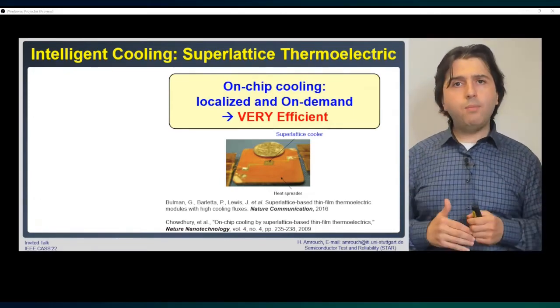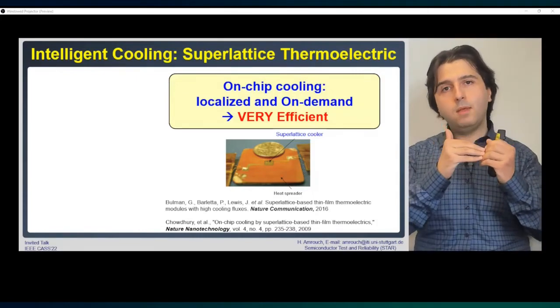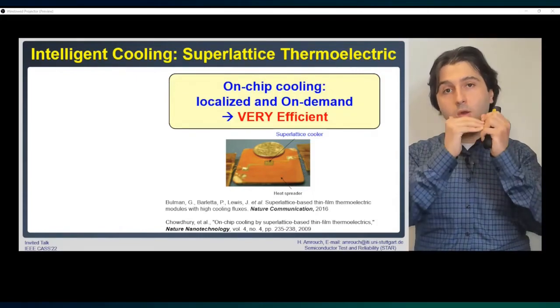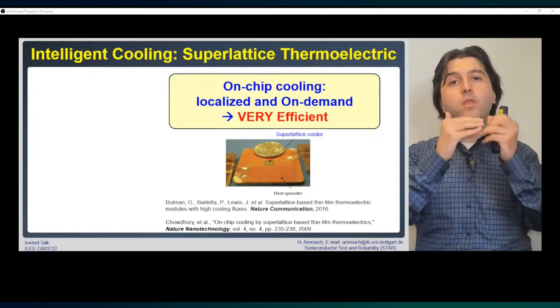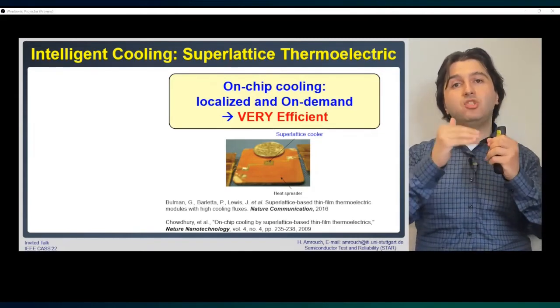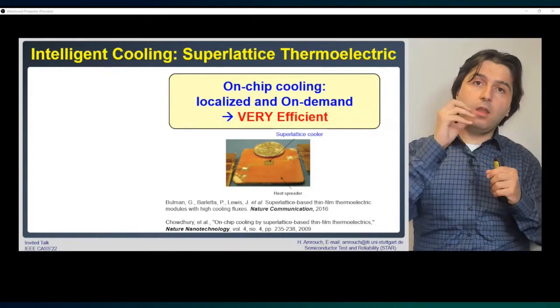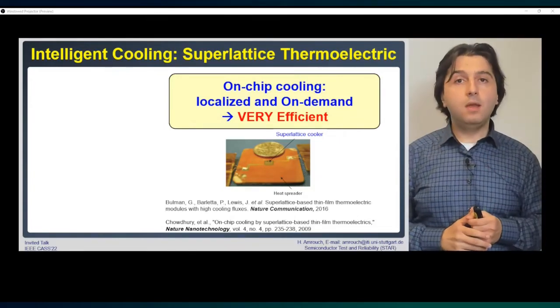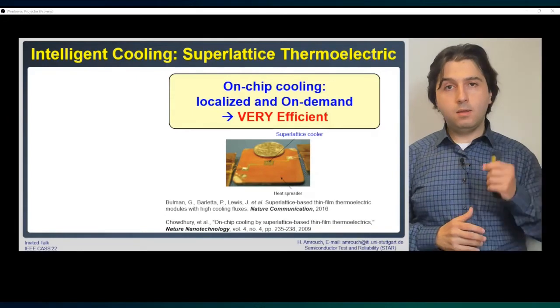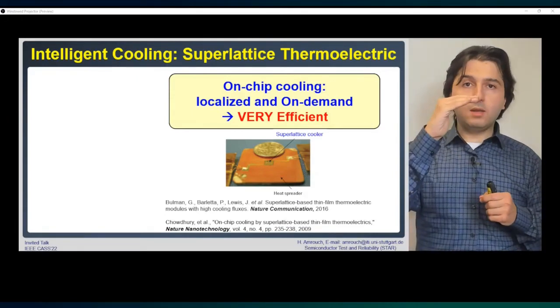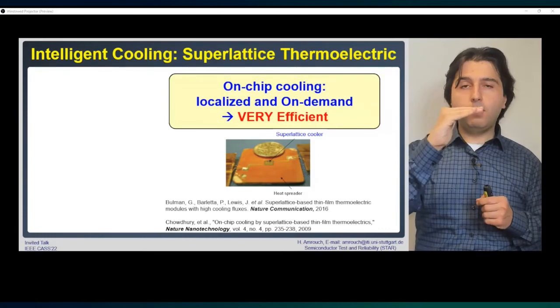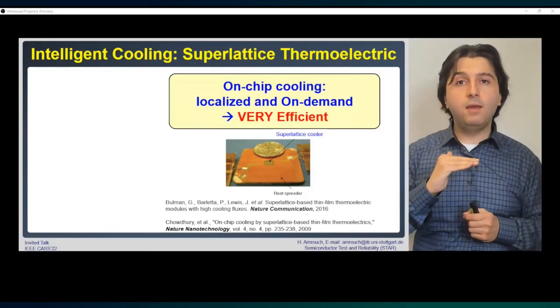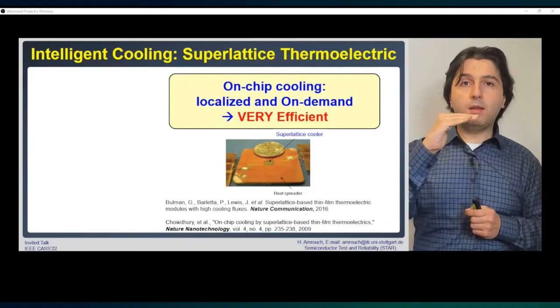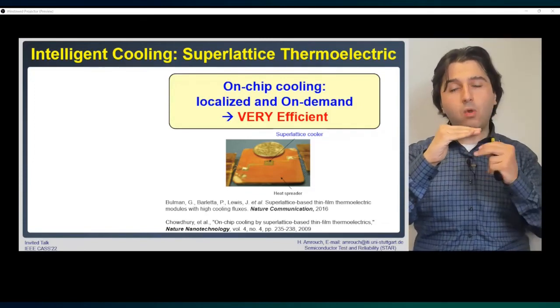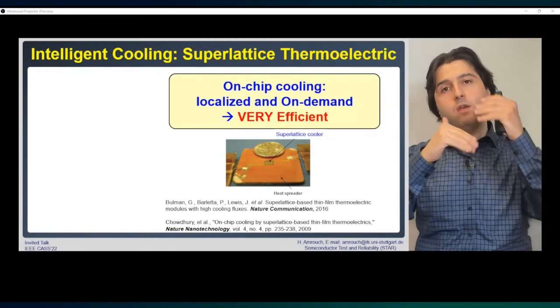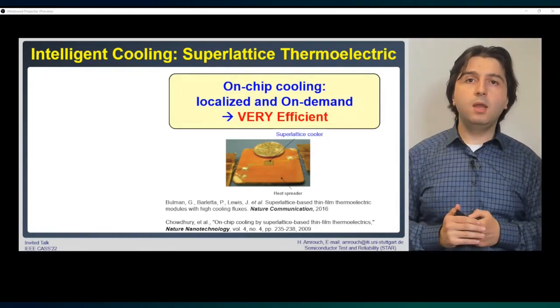Those types of solutions allow you to embed a thermoelectric device, which is ultra thin, a few micrometers, within the chip die itself, and hence generate an effective cooling effect through the Peltier effect. So you put the thermoelectric device on top of your hotspot. The thermoelectric device employs the well-known Peltier effect, which will make one side of the thermoelectric very cold, which is where you want to cool down the chip, and one side very hot, but it will be dissipated through the packaging and the heatsink.